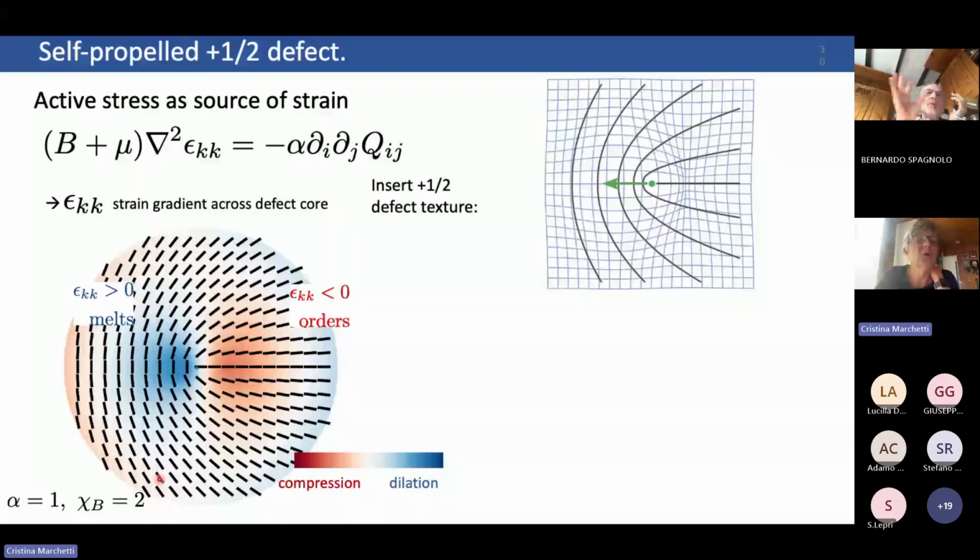So there is a mechanism for motion of the defect here, which is not through flux of material, but simply due to remodeling of the structure due to this sort of strain melting effect. It's sort of like dominoes falling, if you like. When you have dominoes and you get them to fall in particular patterns, nobody's moving, no pieces of dominoes are being transported, but they're just reorganizing.